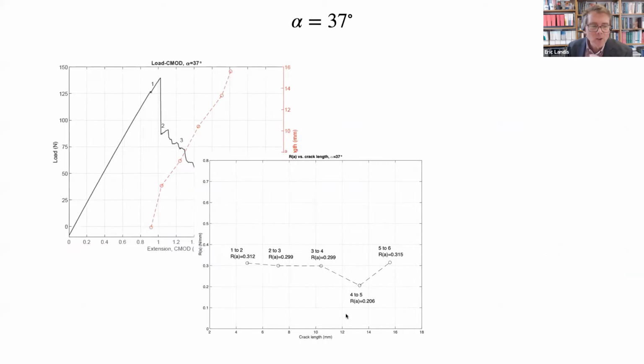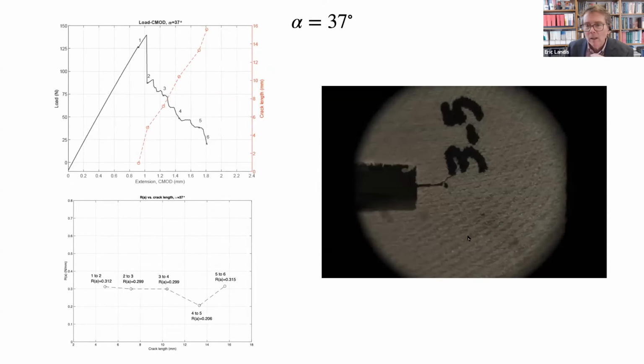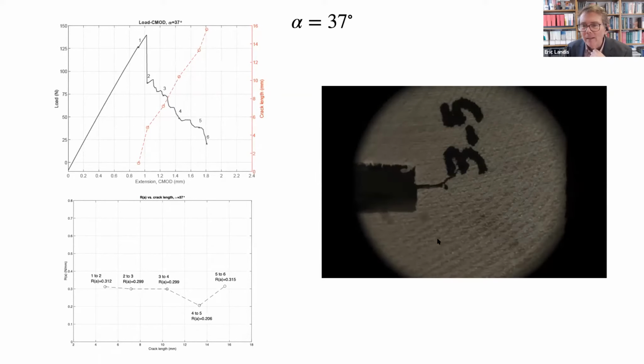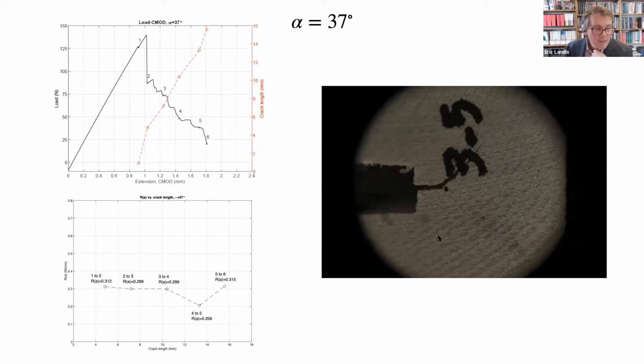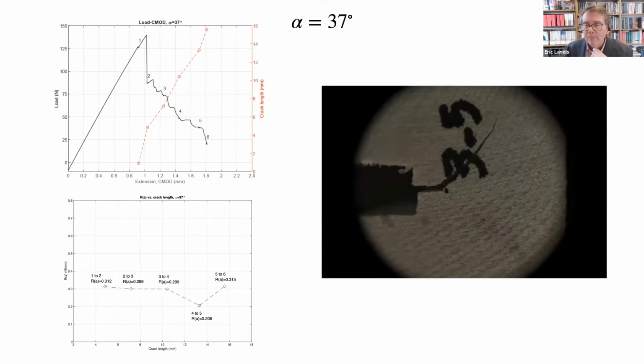Let's see how that compares with how the cracks grow. Well, unfortunately, the cracks grew right through our label, but here again, the crack simply propagates along this early wood region. Now, of course, fracture theory tells us that if this were a homogeneous elastic material, to maximize strain energy release rate, we'd want to go straight. But because of this lower resistance, the crack curves.